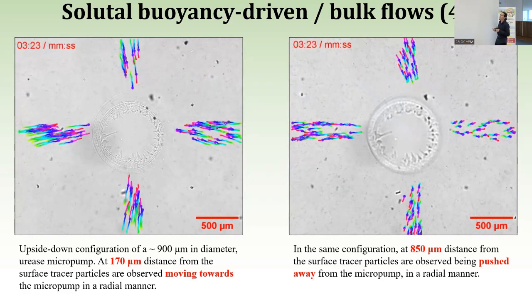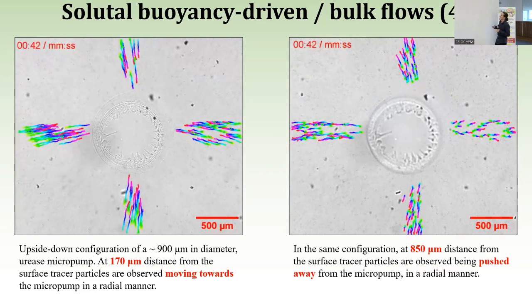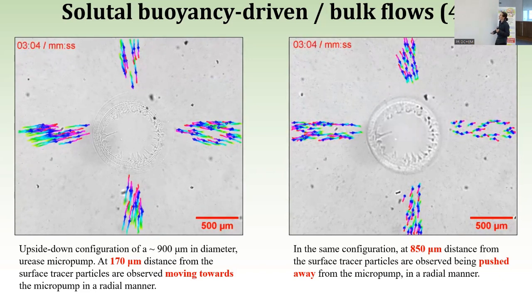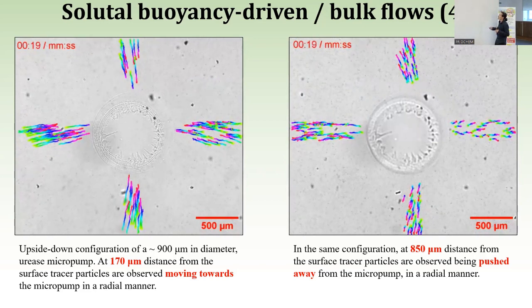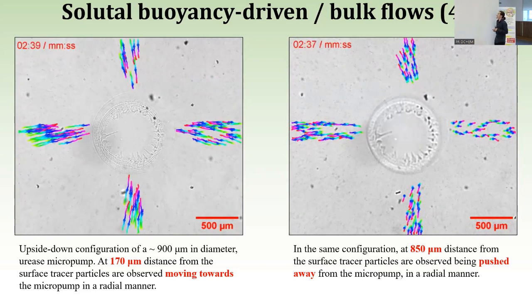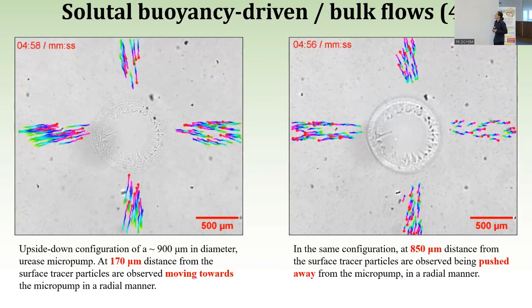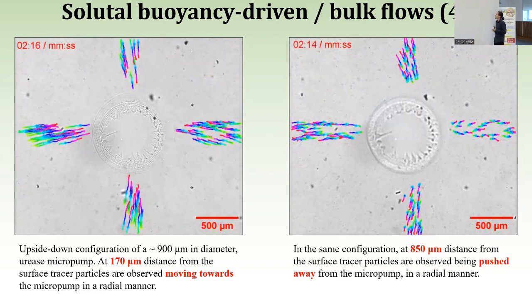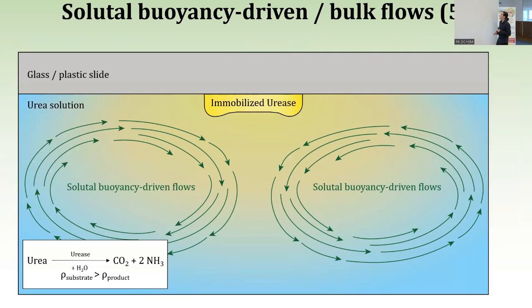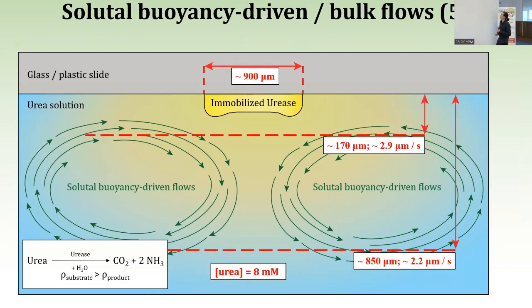So at 170 distance, this time below, the tracer particles were moving towards the micropump instead of being pushed away. And at 850 below, the tracer particles were being pushed away. So again, this is the schematic explanation. The same pump, this time turned upside down, generates a convective flow that moves inward.